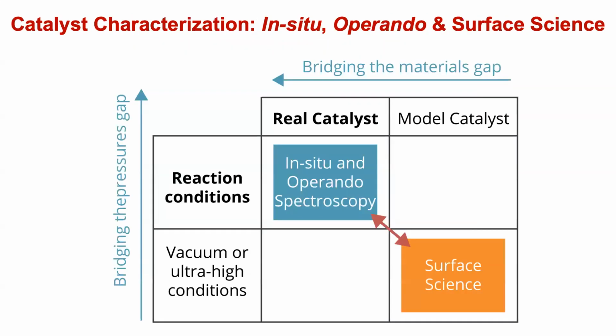Now, this whole challenge in catalysis, where you try to push the system to the level that it becomes interesting, real catalyst, real reaction conditions, this is the field of in situ operando. So actually you're bridging the pressure or temperature gap, bridging the materials gap. That remains a challenge until today. Are we going to the most complex system and the most realistic conditions, but give in on information? Or are we going into model systems? And both actually have their merits.